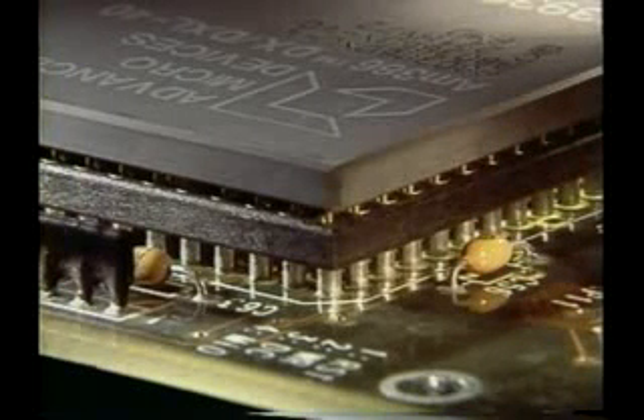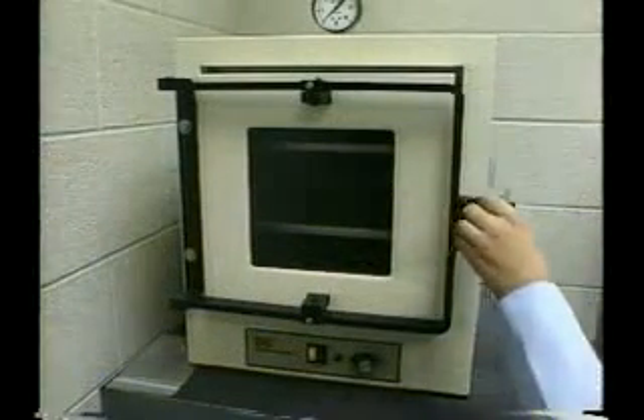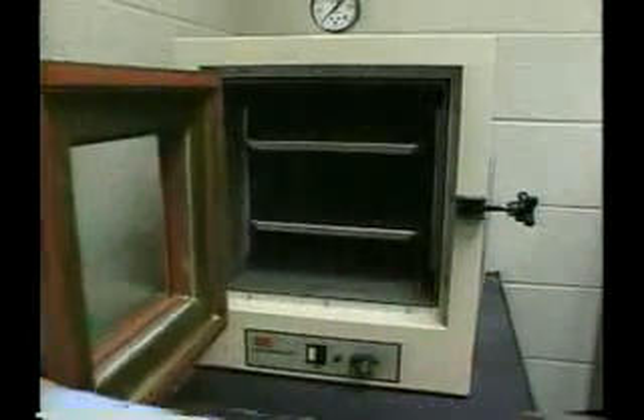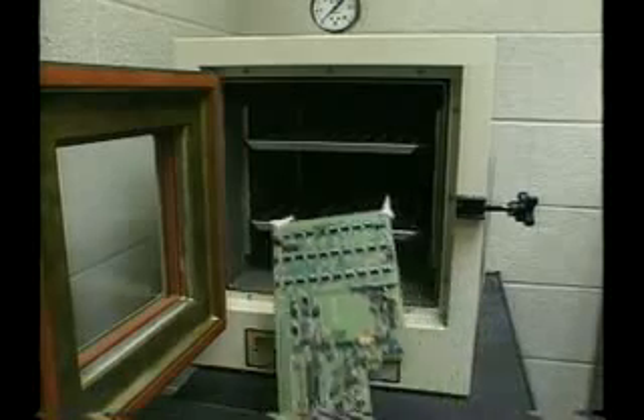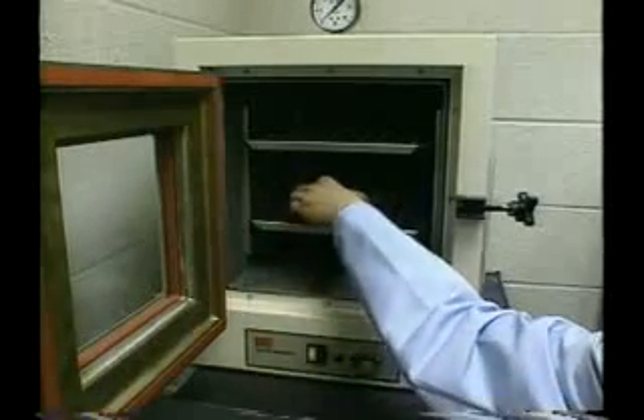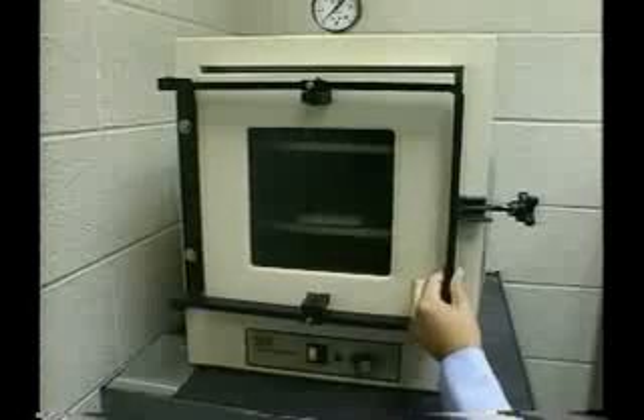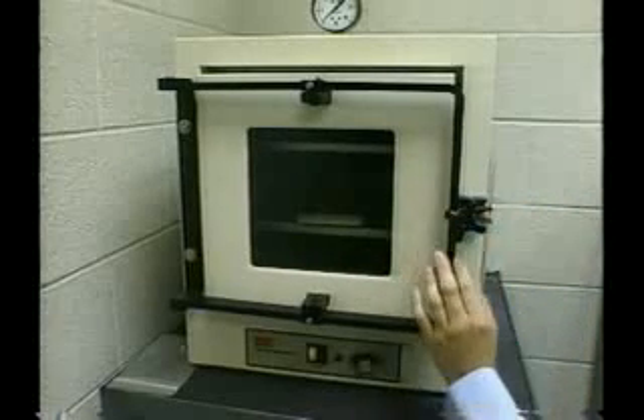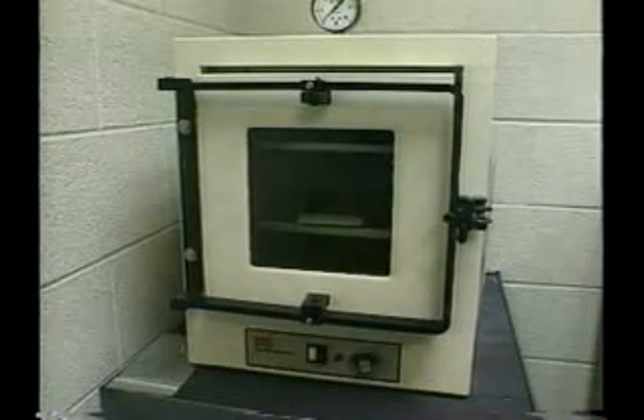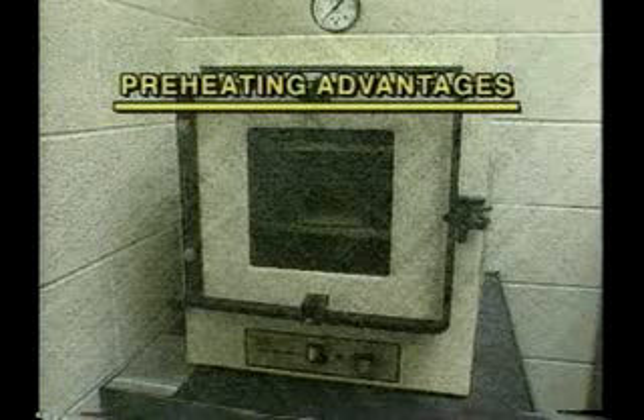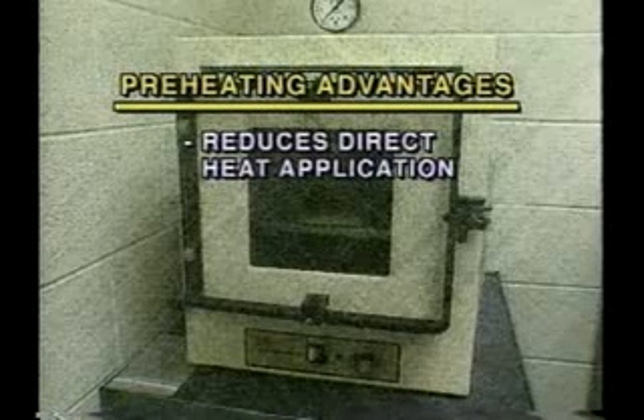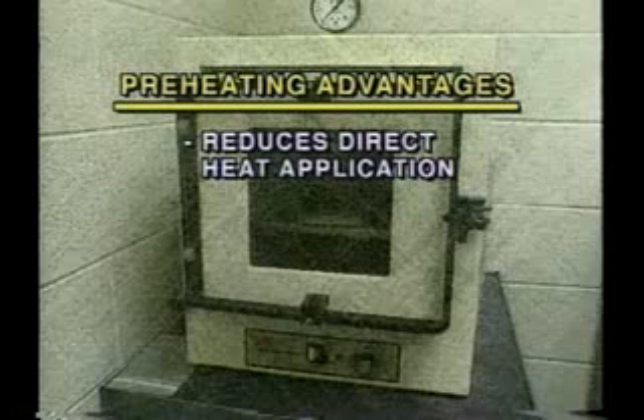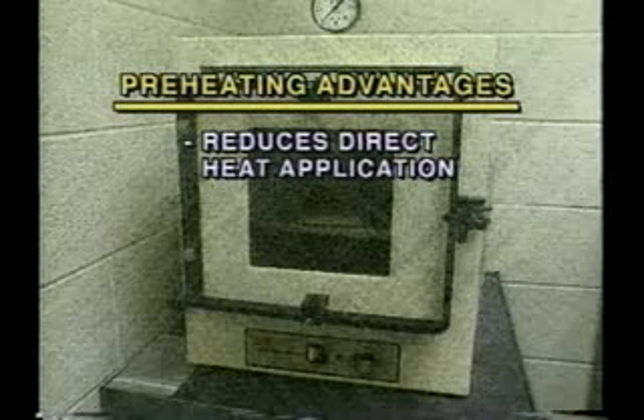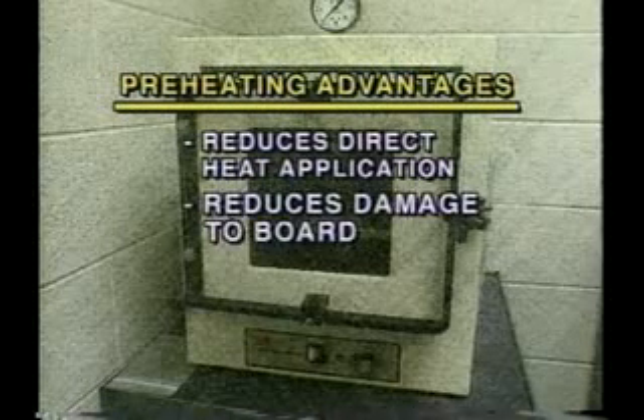Another technique that can be helpful when you can't access the leads on the component side of the board or during multi-layer rework is to preheat the assembly prior to the rework operation. This can be done in a convection oven or on specially designed local area preheaters. It can take a few minutes to bring the temperature up to 100 degrees C, but preheating does have some distinct benefits. First, it reduces the amount of direct heat required to melt the entire solder joint. This can reduce the chance of potential damage to the board.